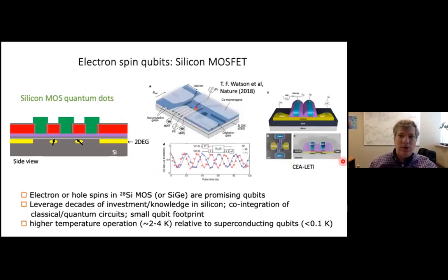So when it comes to quantum computing with spins, or spin qubits, in semiconductors, III-V semiconductors like gallium arsenide that I've been talking about earlier have the issue of nuclear spins in the lattice that you can't get rid of by isotopic purification, because all of the isotopes in columns 3 and 5 of the periodic table have nuclear spin. For silicon, however, we can remove the silicon-29 nuclear spins and be left with a spin-free silicon-28 lattice. So this greatly increases the coherence times of electron spins confined in quantum dots, making that a good candidate for a scalable qubit system.